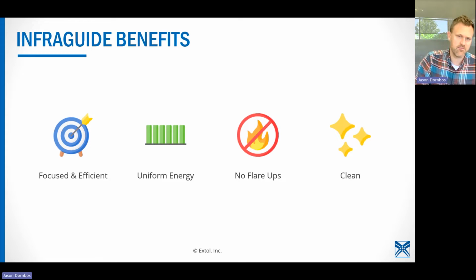So that leads to some of the benefits of InfraGuide. It's focused and efficient. Rather than trying to mask off where the energy can go, we're just taking all of the energy and focusing it right on the weld rib, and it's not focused anywhere else, so it's not getting absorbed and heating up other areas of the part. It's got uniform energy. Like we've mentioned a couple of times now, you can tune every single bulb independently. You can adjust the rate of heating. You can adjust the amount of time that the lamp is on. And that's really all you need to control the rate at which your parts are heating up.